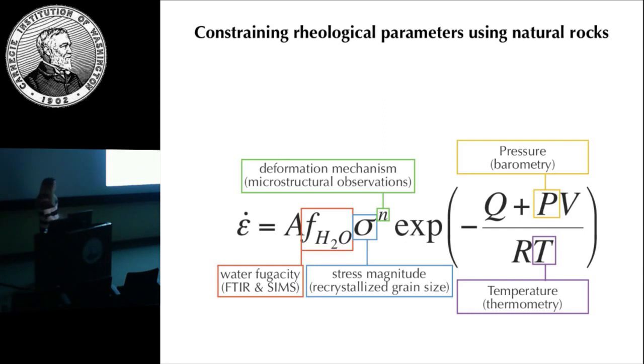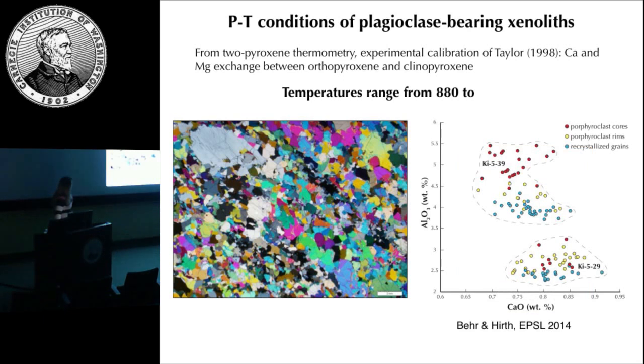So we can again come back to this and we can use the xenoliths to constrain a bunch of these rheological parameters in natural rocks. So water fugacity, stress magnitude, temperature, pressure, etc. So I'll go through and show you some of those. So this one I showed earlier is actually from the Cima volcanic field. And from two-pyroxene thermometry, we get temperatures ranging from 880 to 1050. Sorry, that's missing there. And like I said, we're very careful to distinguish, whenever I say these temperatures, I'm talking about the deformation temperature represented by the recrystallized grains as opposed to the host porphyroclasts that clearly record higher temperatures and represent cooling.